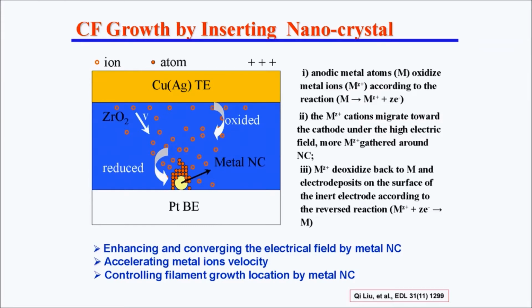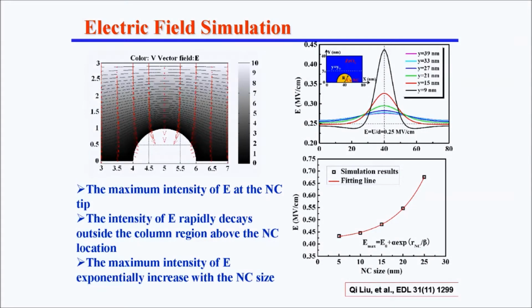So based on this idea, if in this device we add a nanocrystal here, anything with a tip is also okay, when stressed, the highest electric field is at the top here, then maybe we can induce the filament forming along these areas. That's our idea. So we do some simulation. We can clearly see the highest electric field is just on the tip of this nanocrystal. Except for this tip, the electric field decreases dramatically.